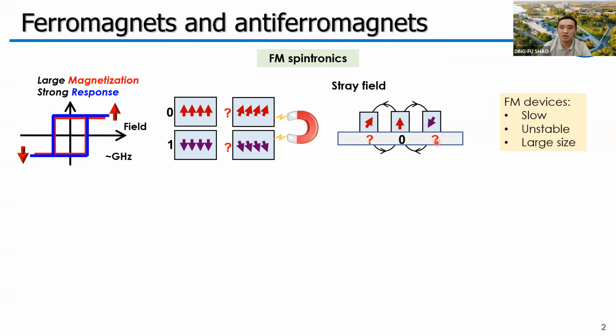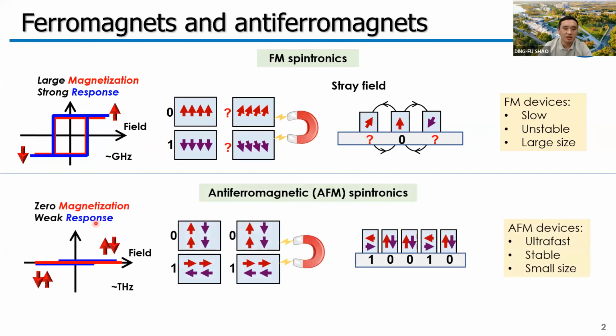In order to overcome this problem, we have to move the device units far away from each other, which is not good for high density applications. On the other hand, antiferromagnets do not have these problems. The dynamics is about terahertz, indicating ultra-fast speed. And the zero magnetization makes antiferromagnets very robust against the magnetic field. The zero magnetization also indicates the absence of stray field, so that we can put the device units close to each other, which is wonderful for high density applications. So antiferromagnets are very suitable for spintronic applications with high speed, high stability, and high density.